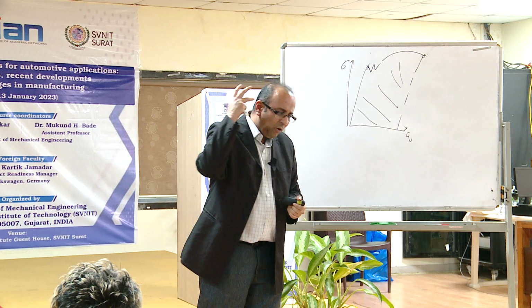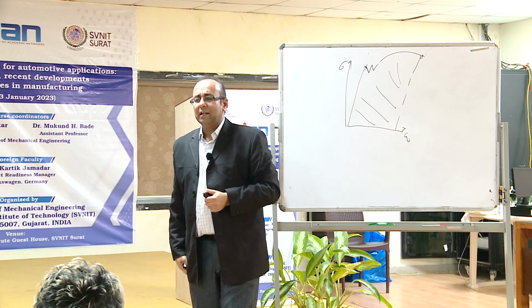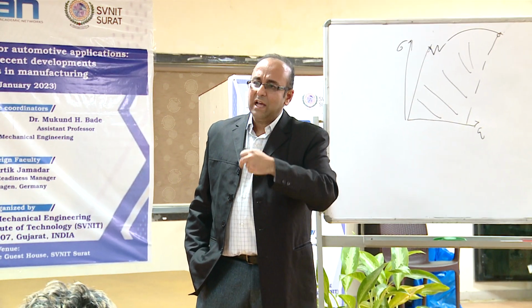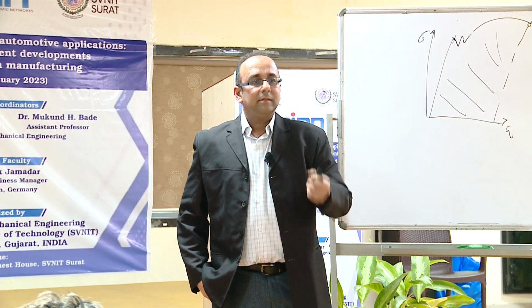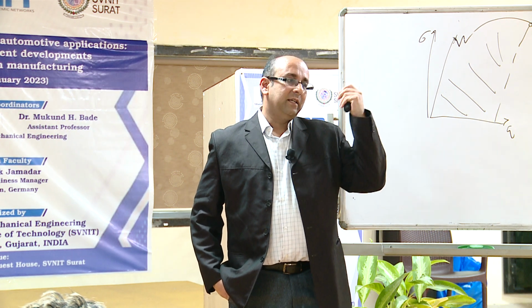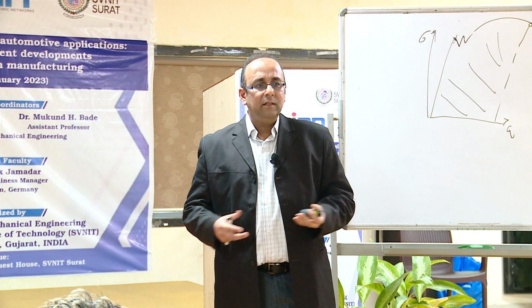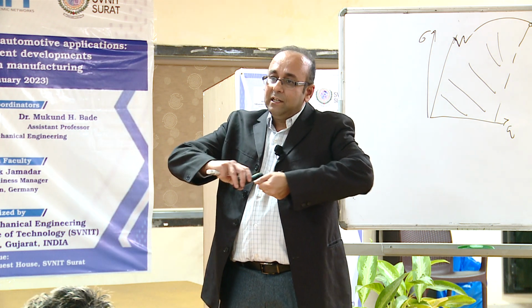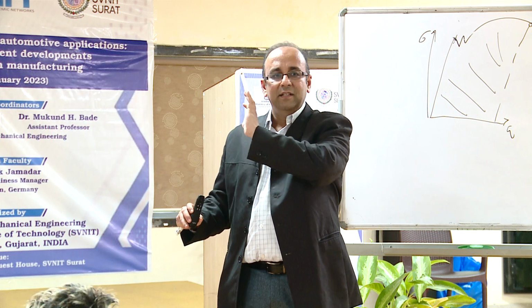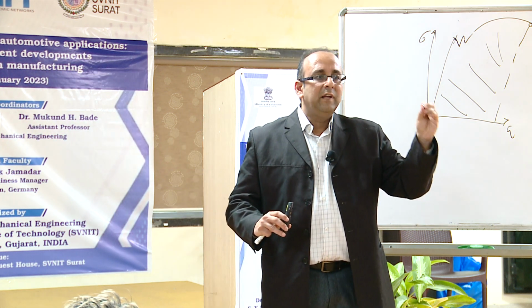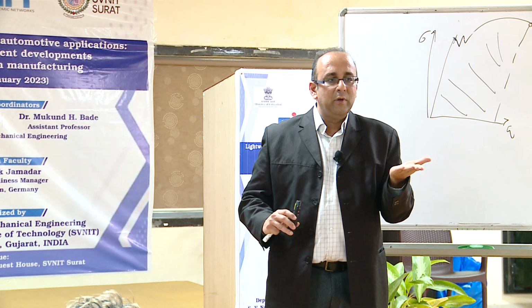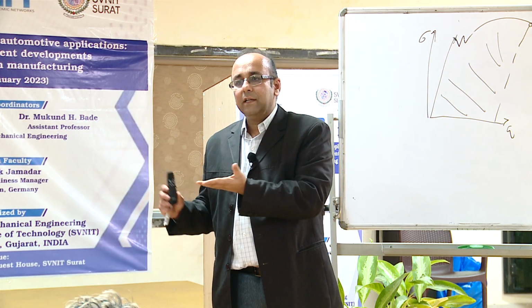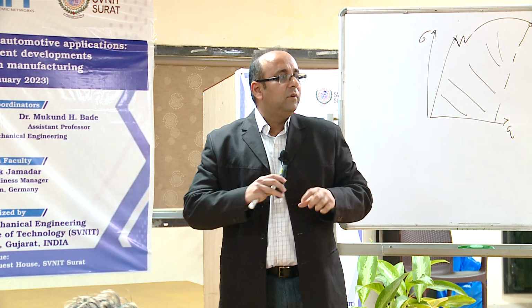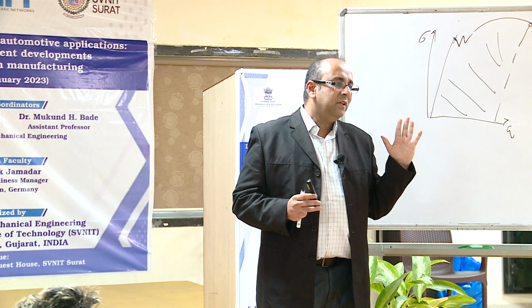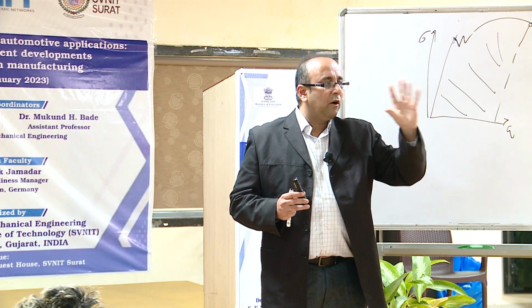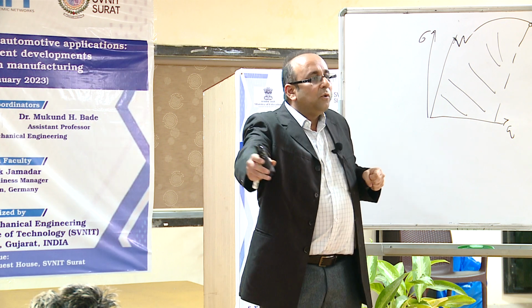Now people thought, why do I always have to use the temperature to increase the martensite strength? Is it not possible to avoid this temperature completely? Yes, and that's how the steel started emerging, TRIP steel or TWIP steel. What is that steel? Austenite, but by deformation, that austenite converts to martensite. Transformation induced plasticity or twinning induced plasticity. So basically what we are doing, instead of temperature, we are giving mechanical force to convert that. Finally we are getting martensite structure, but it is not 100% martensite because some austenite will remain. That's why we are also getting high deformation possible.